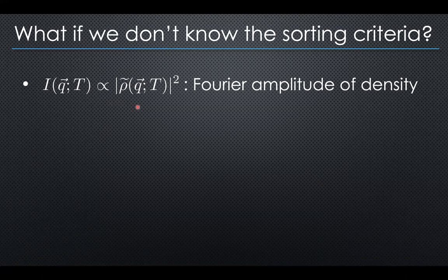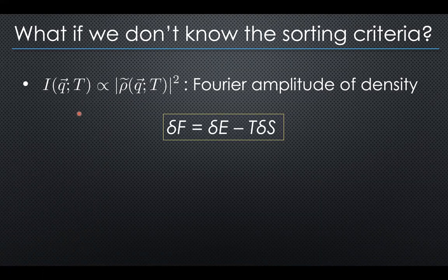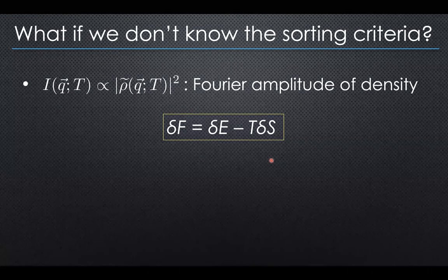Now, often measurements are done with some control parameter. The sample is there and you scatter while you're rotating the sample, but you also change something else. There is a control parameter. It could be pressure, could be doping, it could be some other type of control, but typically there is a control parameter. And temperature is the most common control parameter because that is really what tells us the difference between what the Hamiltonian wants and what the entropy will do. So the innate property of the system, the interactions, determine what is the energy that a given configuration of my charge would have. And then there is an entropy driving the randomness, and temperature is what's setting the balance between the two.